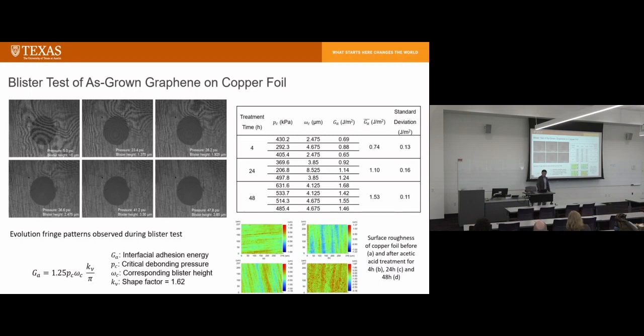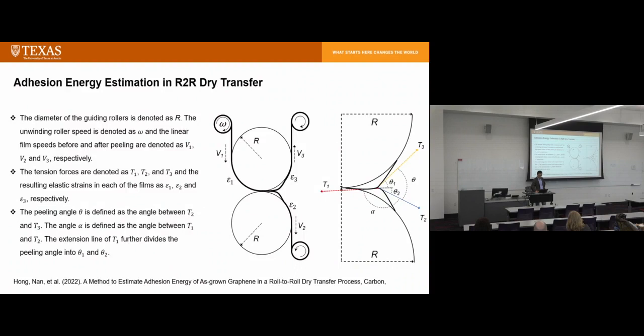adhesive energy. So our measurements are between 0.74 to 1.53, depending on the surface roughness of the sample. So we also characterize the surface roughness of the copper, and then determine what is the adhesive energy, the as-grown graphene adhesive energy. So this is the first time that people have reported as-grown graphene adhesive energy using a standard method.